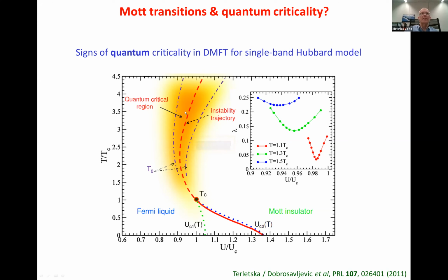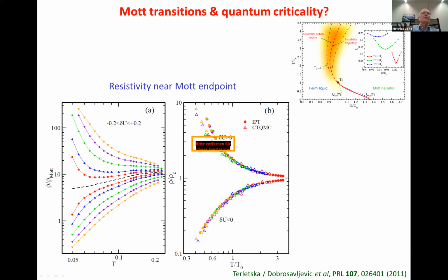So what has been seen? This is shown here on this slide. The resistivity has been calculated again within DMFT, and is now shown along a number of trajectories in the left-hand plot as a function of temperature. These are trajectories which run in parallel to the red dashed line, labeled the instability trajectory in the phase diagram, which you see on the upper right.